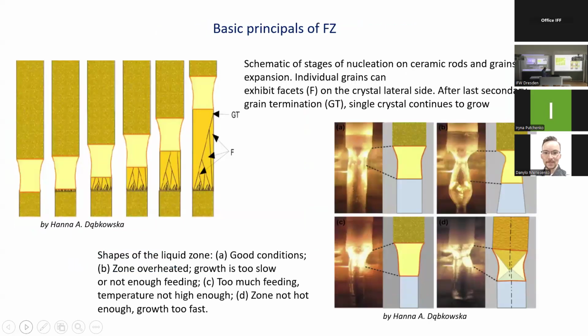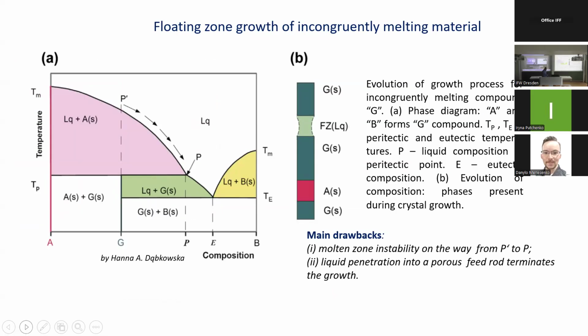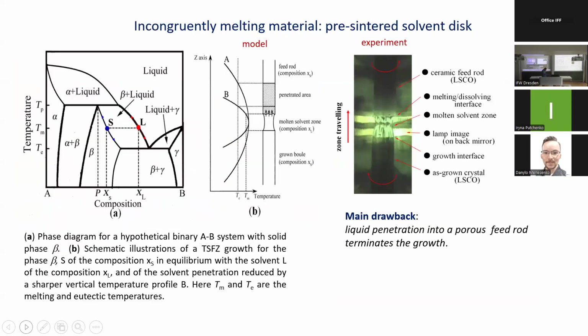Here you see the basic principles of the floating zone technique. Once you start the growth on a ceramic seed, you get multi-grain growth, but sooner or later, due to the effective grain selection in this technique, you get single crystal growth. And this picture illustrates how we could control the growth conditions, because in this technique we could not directly measure the melt temperature, so we rely on the shape of the molten zone. So this one is more or less a perfect or good shape. It means people have found nearly optimal growth conditions. Here, here, and here, the shape is not good.